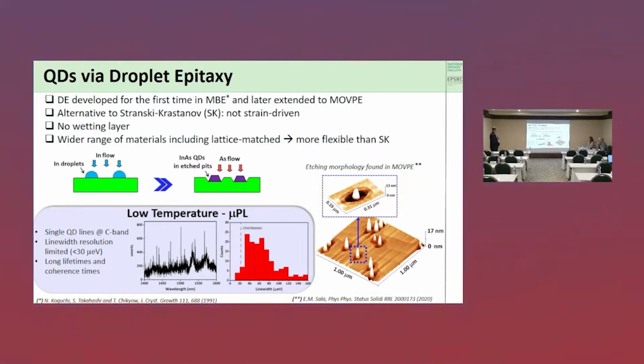One of the advantages is that we have no wetting layer, as in the Stranski-Krastanov method. When you have your quantum dots, you have a wetting layer associated with the original thin layer of indium arsenide that you grow, and that can be problematic in a variety of devices, particularly introducing competitive recombination routes and noise into the structure. So we have established over a number of years the growth of indium arsenide quantum dots at 1550 nanometers using droplet epitaxy in MOVPE, and here's an example of an optical spectrum in the C-band, and you can see these sharp lines here are associated with individual quantum dots.